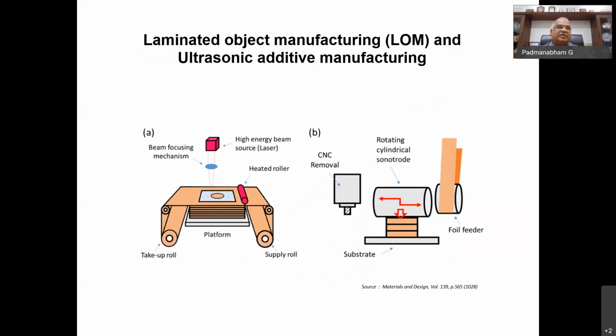There is also another method where you don't use a heat source, but ultrasonic. Heat source also you can use, and even ultrasonic sources you can use, where the feedstock is neither powder nor wire. It is a foil. Foil after foil you can place to build the layer, and that layer is fused one to the other, and then you build the component. So it is a kind of solid state method. You are applying force to jam up layer to layer.